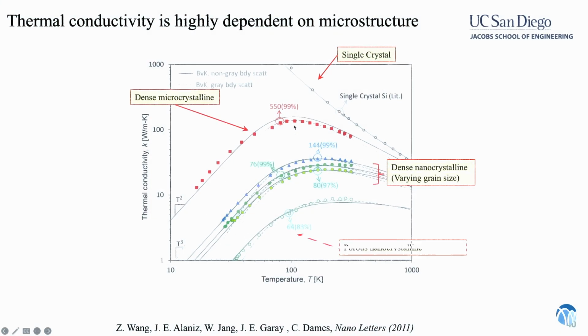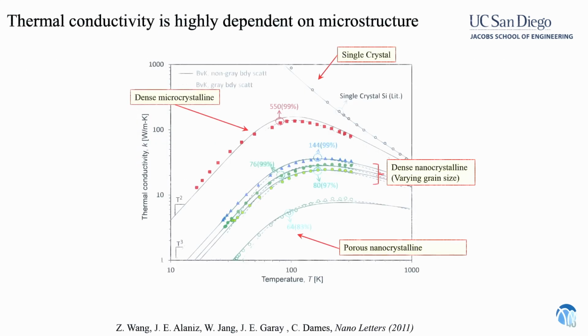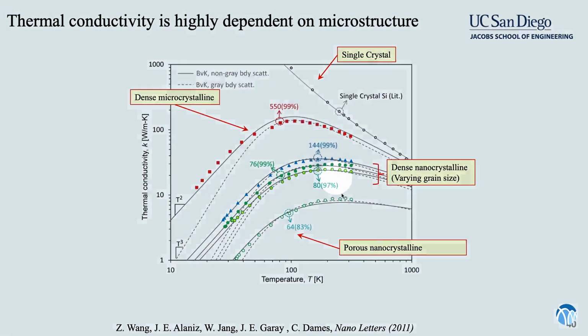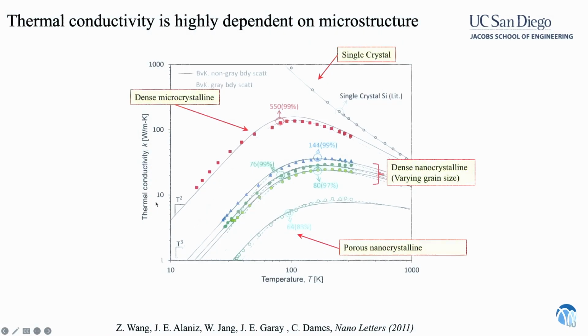In fact, if I decrease the grain size by a lot, I can decrease the thermal conductivity by orders of magnitude, and if I put voids in, I'm decreasing the thermal conductivity by several orders of magnitude. So again, this material is very different. Even though I haven't changed the composition, it's pure silicon. I haven't added or decreased the different types of atoms. I've only changed the microstructure.